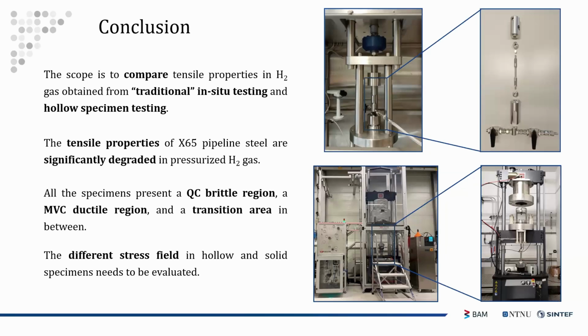And also for all these specimens, we figured out that there is the presence of a quasi-cleavage brittle region, a microvoid coalescence ductile region, and also a transition zone in between. In the future, we will evaluate the different stress fields in hollow and solid specimens in order to better understand the physics behind these tests and to better understand how this stress field impacts the susceptibility of the material and of the steels under different testing conditions.